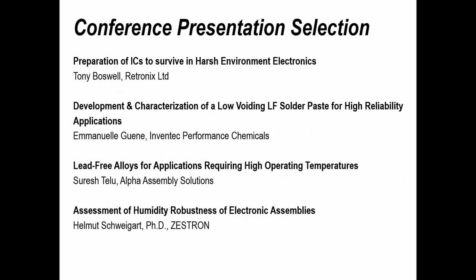Now, in terms of presentations, there's a lot going on, as Keith's already mentioned, so I just wanted to pick up on a couple of them. Presentation by Tony Boswell, looking at components. Now, there are a number of components which we do know we see early failures on, and this is solder joint failures. We know for a fact that within the automotive industry, a lot of companies have gone to QFN, LGA type packages, and there have been early life failures. You know, that's a fact. So solder joint failures, probably due to expansion and contraction of the package. So what he's done is looked at different techniques to overcome that.